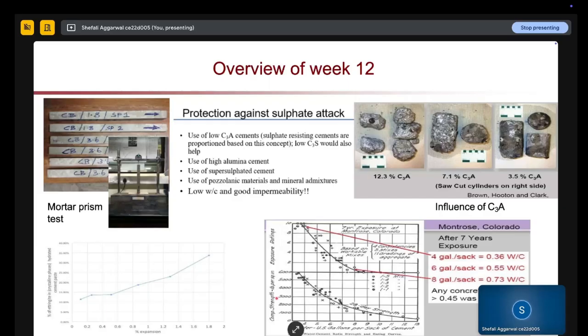Another thing is how your water to cement ratio and other factors are affecting your expansion rate. This is a PCA study done on a similar basis: this is your strength value, this is your exposure rating, and here we are talking about water to cement ratio. It is not given as what we use nowadays, like 0.36 or 0.55, but as water in US gallons per sack of cement. Based on that, we see how your strength and exposure rating change. If you have more C3A and more ettringite formation, because of higher water your strength will decrease.